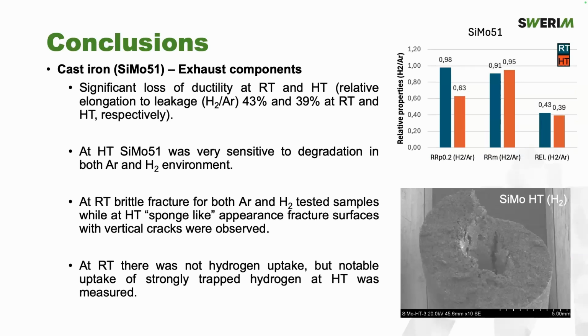SiMo51 material, significant loss of properties, ductility at room and high temperature. You can just see the numbers there, how much we have reduced the ductility, the elongation to fracture. At high temperature, this material was very sensitive. I already explained our assumptions. We saw a brittle fracture mode for both argon and hydrogen at room temperature, and sponge-like, you can see this vertical crack on the slide at high temperature. And at room temperature, we didn't see any uptake, but notable uptake of hydrogen at high temperature.